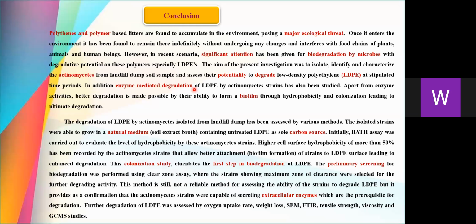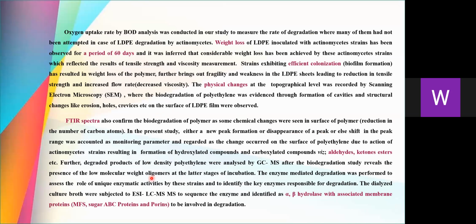The enzyme-mediated degradation by actinomycete strains has also been studied. Apart from enzyme activity, better degradation is made possible by the ability to form biofilm. Further analysis was done by biofilm formation, bacterial adherence test, oxygen uptake rate, and physical changes by SEM, FTIR, and GCMS. The physical changes showed major changes in the surface of the LDPE film. FTIR spectrum showed the formation of new functional groups, and also a change in the existing functional groups. Under GCMS analysis, low molecular weight oligomers were identified.